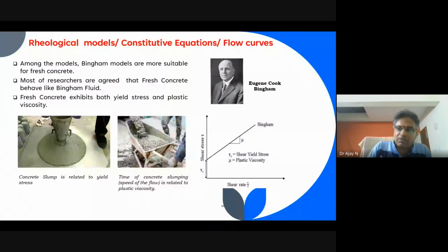And the time taken to travel and fill up the formwork, we can call the viscosity. So both these parameters we can fit in the Bingham equation. Therefore, many researchers have clearly proved that this equation and this flow curve fit the fresh properties of concrete. So this is used for all the rheological properties of concrete, using yield stress and viscosity. And